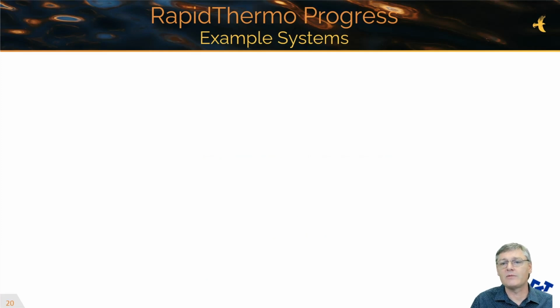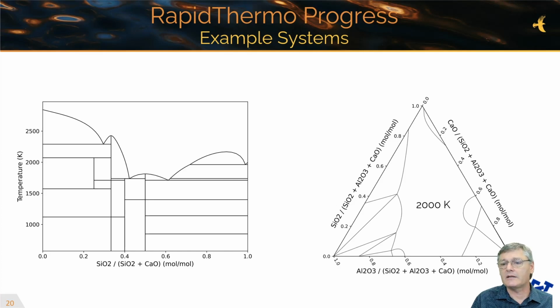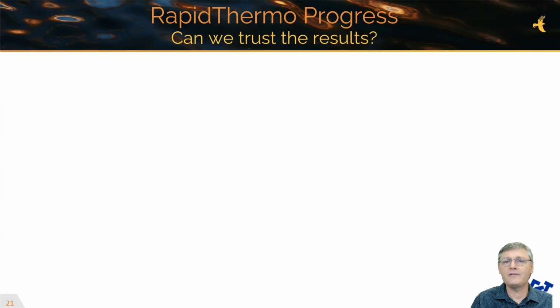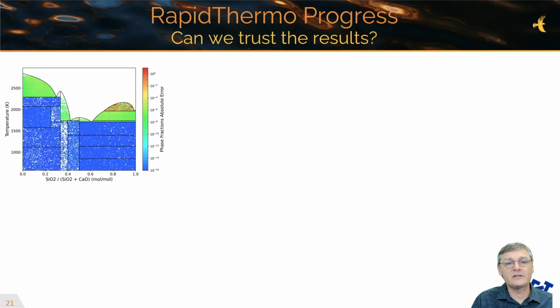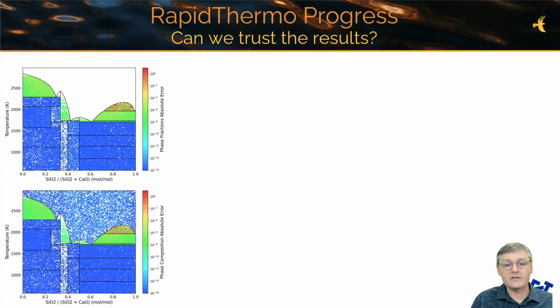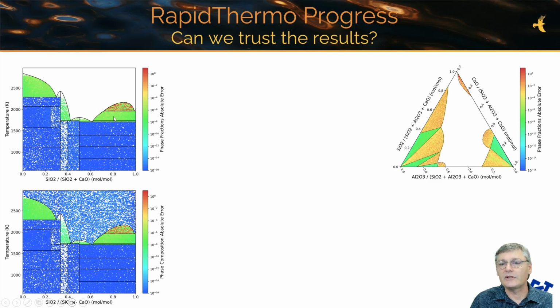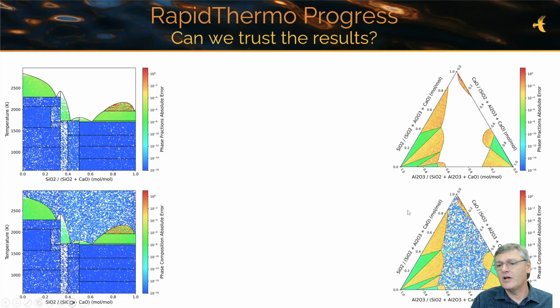Now the example systems that I will demonstrate with are these two phase diagrams, a binary and a ternary slag system. And the first question when you ask a piece of software to act as intermediary between you and ChemApp is whether you can trust the results. If you consider phase fractions and phase compositions in the binary system, you can see that all the blue regions are basically floating point precision errors. The green errors in the two-phase regions are small enough for a multiphysics model. And we do see some problems in the slag region, which is a known problem in our current prototype, which will be fixed shortly.